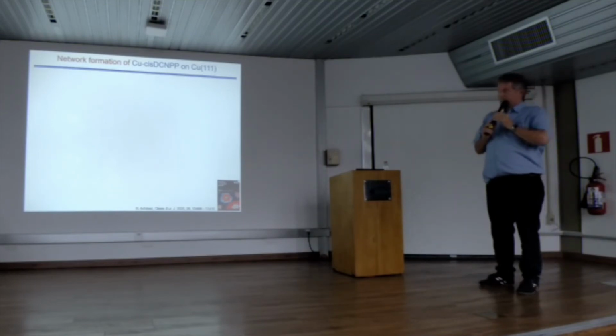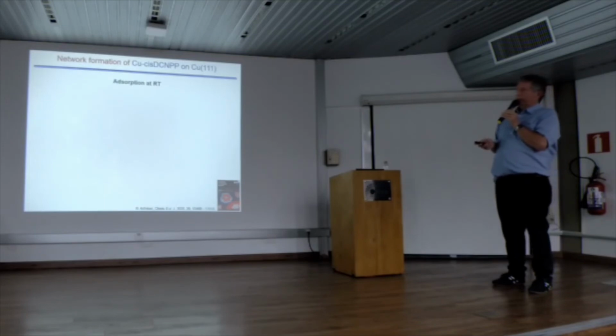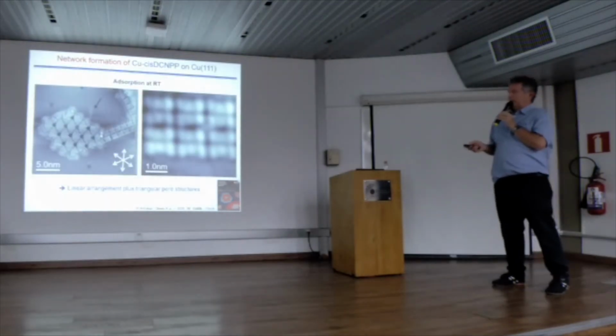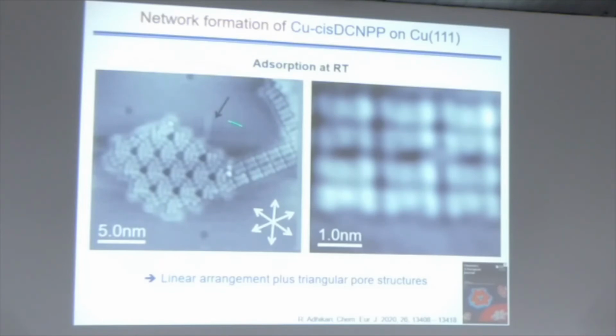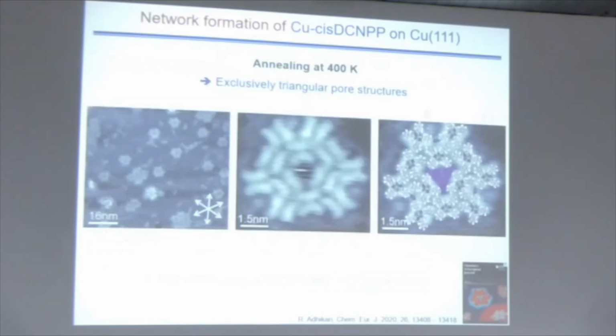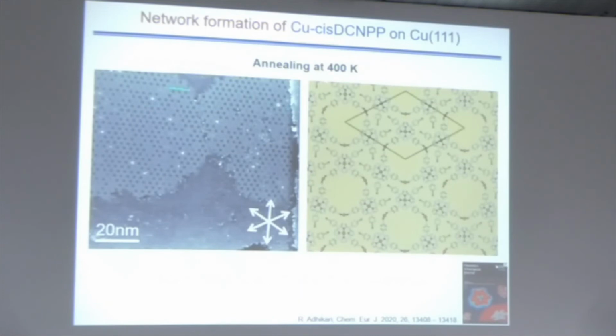This is nearly it concerning metalation. But I want to show you some side effect which is pretty nice if you work with these molecules. If you adsorb them at room temperature, you also find a very nicely ordered structure on the surface, a long-range order structure, and the structures get even nicer if you heat to higher temperatures. You get structures that look like snowflakes, and you can go even further if you heat higher coverages, and you really get well-ordered networks on the surfaces.